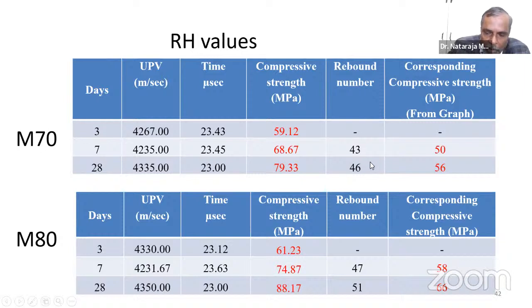But one thing I would like to tell you at this juncture, your rebound hammer is not applicable for high strength. And in fact, even if you see that graph itself, there is a limitation. Anything beyond M70 is not recommended, but your graph only gives you the strength as 50 to 56 based on the observed value of the rebound number, but otherwise your actual strength is much higher. It is not only with M70 but even with M80 concrete.